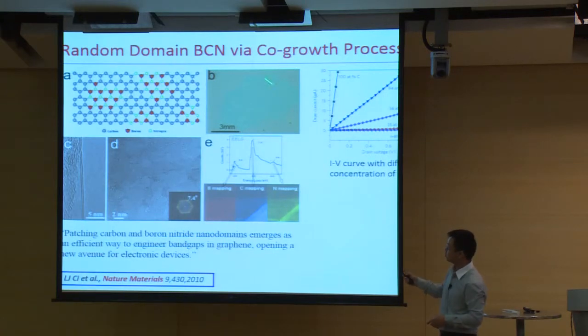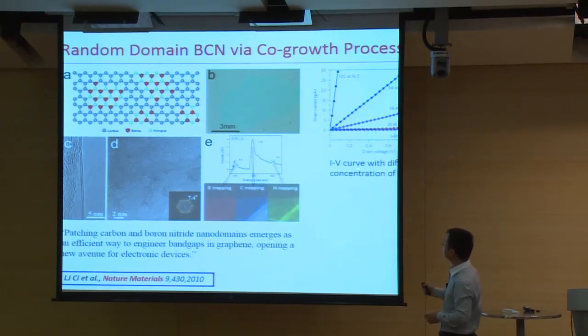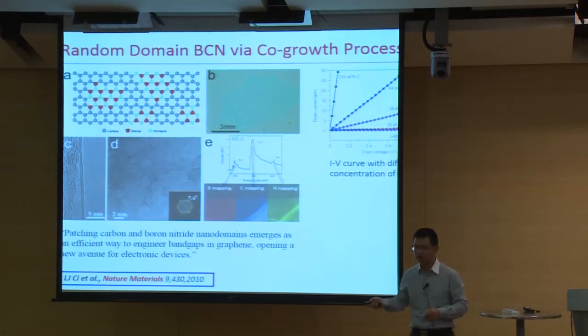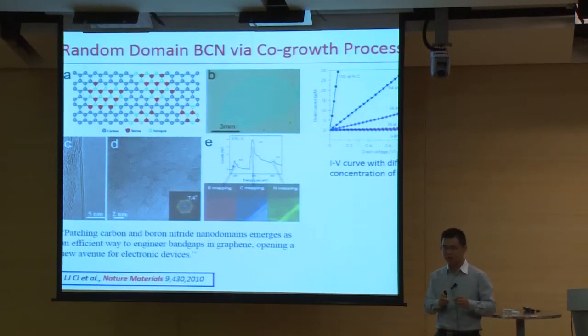It's atomic layers from 2 layers to a few layers. And from the TEM imaging, you can see it consists of boron nitride and graphene domains. The size of the domains is a few nanometers. And we can also tune the concentration of boron nitride from 0 to 70%, so that we can tune the transport behavior of these atomic layers.